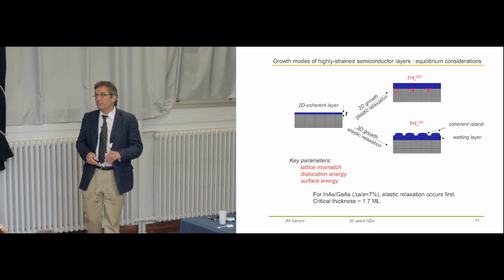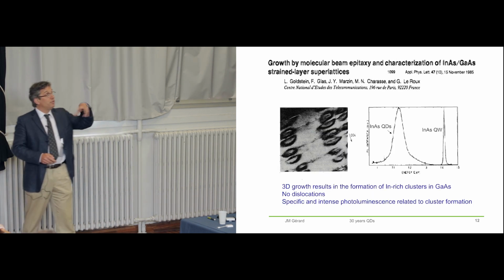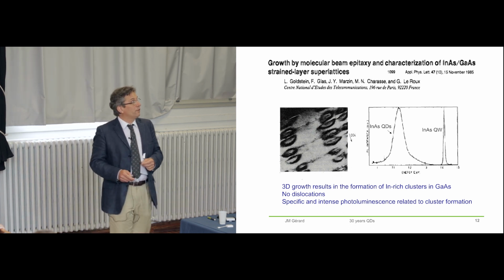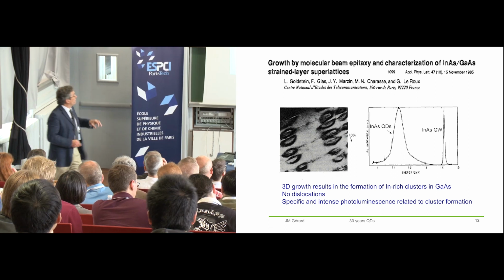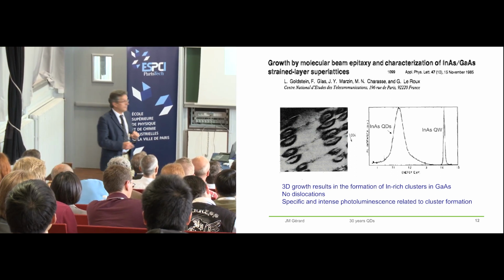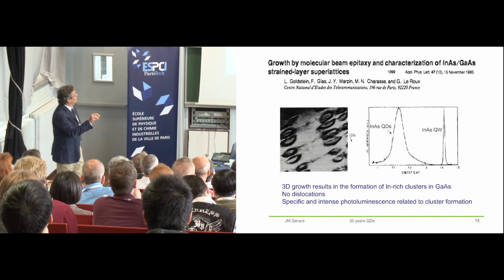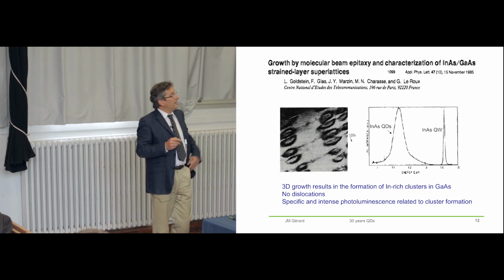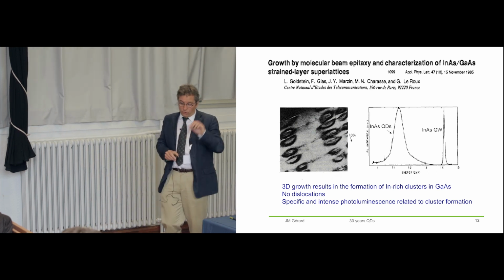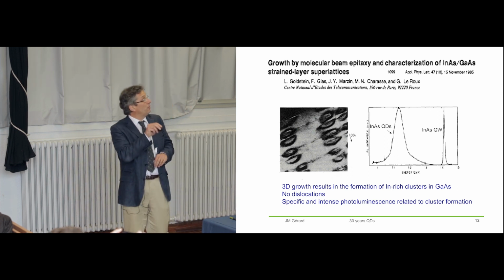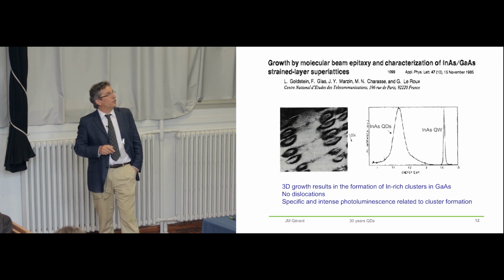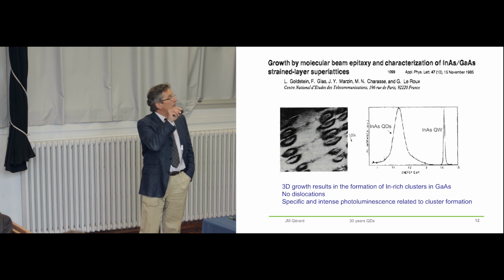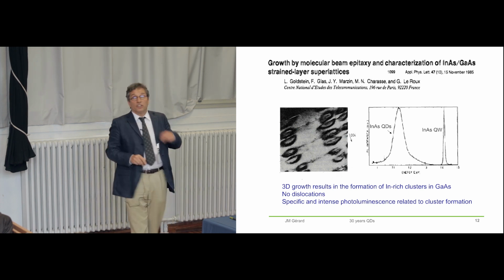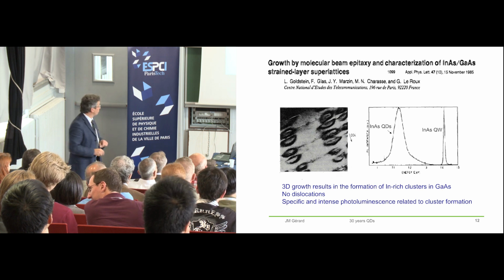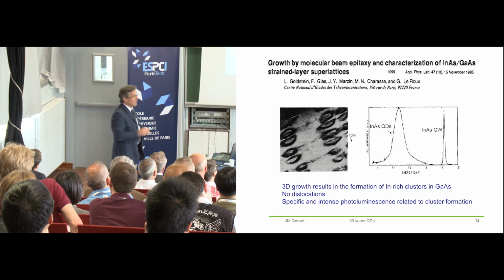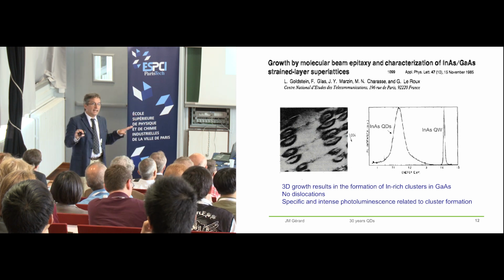Obviously, it was not the first time that 3D growth of semiconductor layers was observed. However, it was the first time that a careful and detailed characterization of the sample was provided. So they studied the sample by TEM, they studied the sample also by photoluminescence, and what they show is that when you observe this spotty pattern using RHEED, you see here clusters inside the semiconductor matrix, which are indium rich, and as soon as you see the clusters, you see a novel, specific, and intense photoluminescence line. Also they could check with TEM that there are no dislocations in the system. The layer is perfectly coherent.